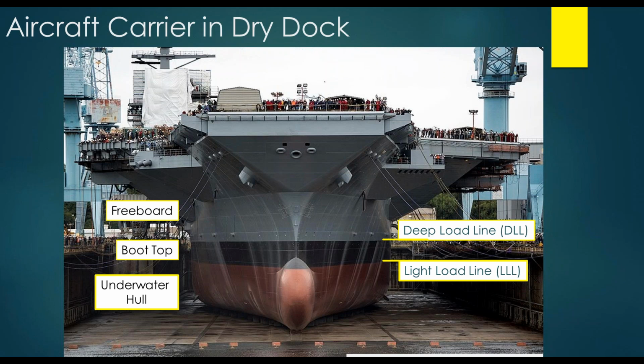As a result of this varying immersion, the environment is going to be different. For example, in the underwater hull and the boot top, you would need an anti-corrosion layer as a primer, top coated with an anti-fouling layer. In contrast, in the freeboard, that area is going to be continually exposed to sunlight, and you would need a coating that has UV stability as the top coat.